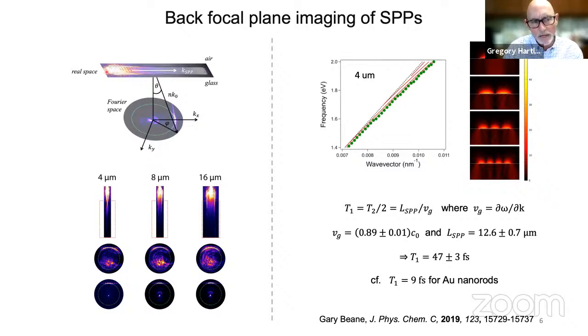So we focus our laser beam at the end of the structure to excite propagating plasmon modes to scoot on down the structure. We're just looking at light scattering, so we're only measuring the leaky modes, the ones at the top of the structure. And then we take a real space image, which is either here or these images here, to measure the propagation length. And then we flip out the lens and we do a Fourier space image to get the wave vector.